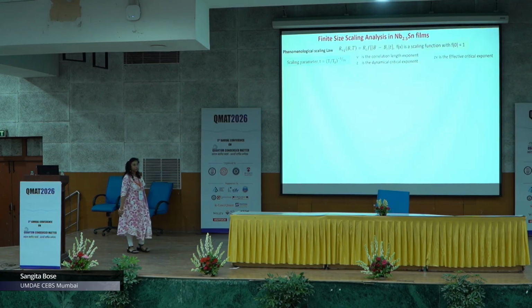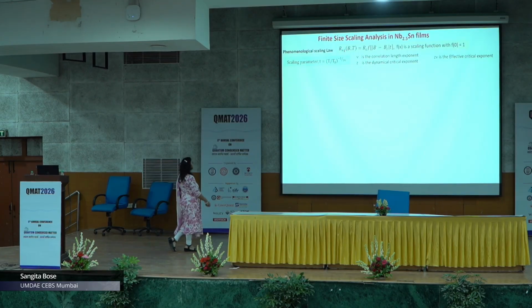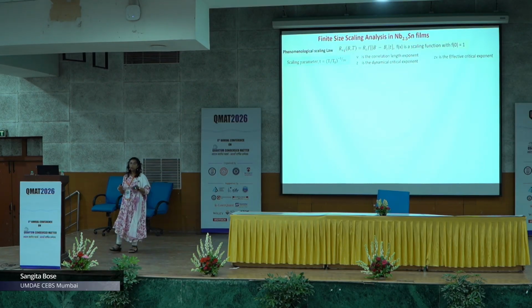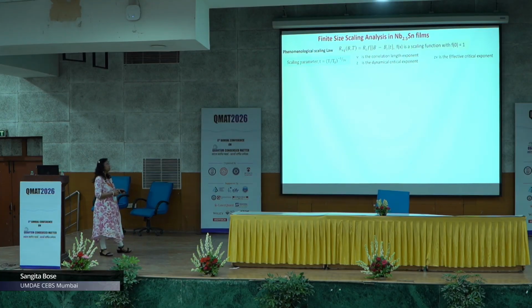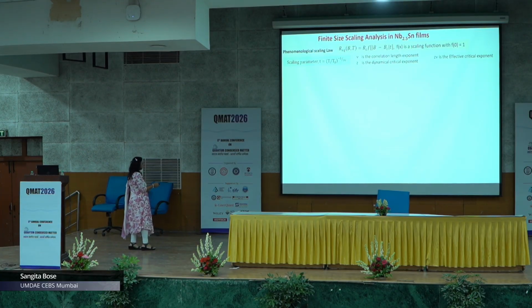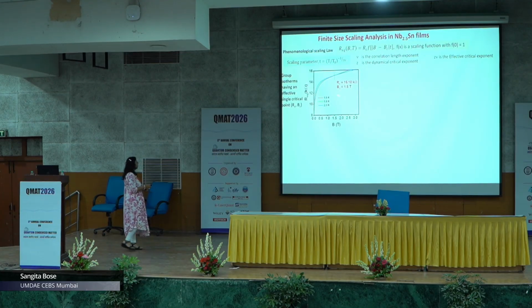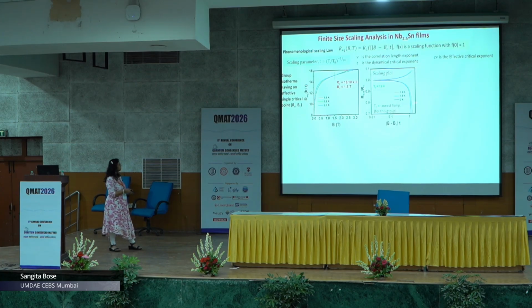However, we cannot rest here just by this experimental thing. So we have to do the finite size scaling analysis to really understand whether we can see the dynamic critical exponent diverging, and so we did the finite scale analysis. So we took isotherms which were very closely spaced in temperature and looked at the crossing point.